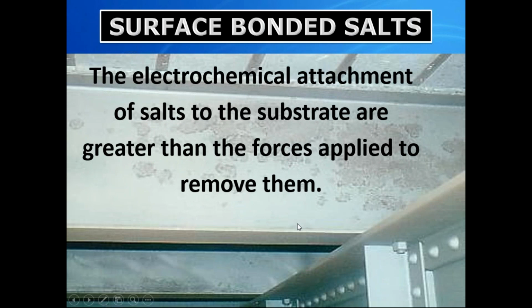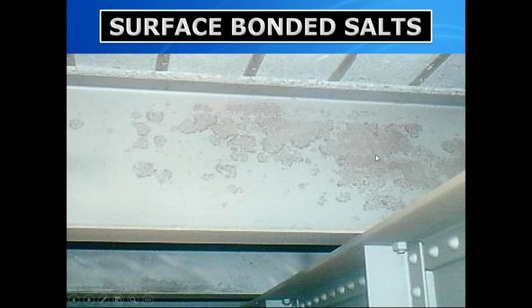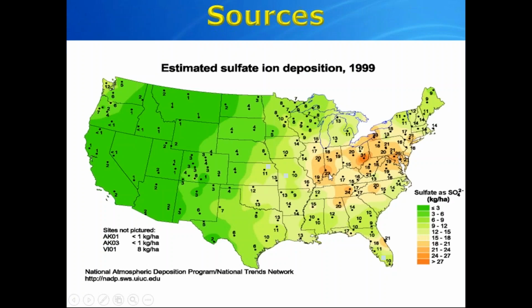People ask, why can't we remove soluble salts just by abrasive blasting alone? Well, the truth is that the electrochemical attachment of salts to the substrate is greater than the forces used to remove them. So looking at all this, you can see where it's starting to turn blackish up in the lightly pitted areas. And I say lightly pitted because that's what it is compared to what we see in the oil patch, where we see some heavy pits, and it's pretty dense. But when you start seeing this take place and you want to test for salts, and we'll get into that in a little bit, these spots up in here are where you actually want to test to see where you are, as well as for removing them.